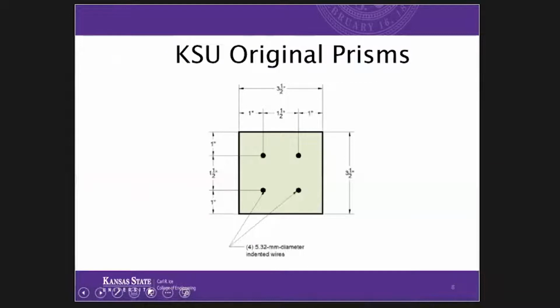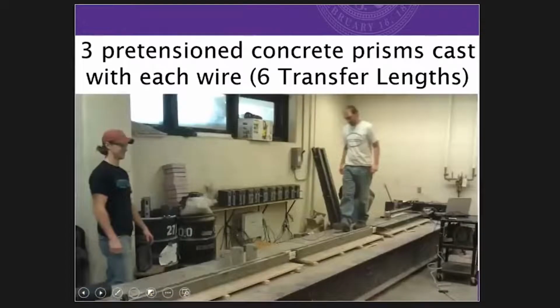So we created prisms. Prism is just a fancy name for a square beam. These were 3.5 inches by 3.5 inches in cross section, and they contained 4 wires that we tensioned to 7,000 pounds. And we could then determine the transfer lengths for those. We actually cast these prisms end to end, 3 at a time, and we determined the transfer length at each end of the prisms. There were 6 transfer lengths determined for each unique set of wire and concrete.